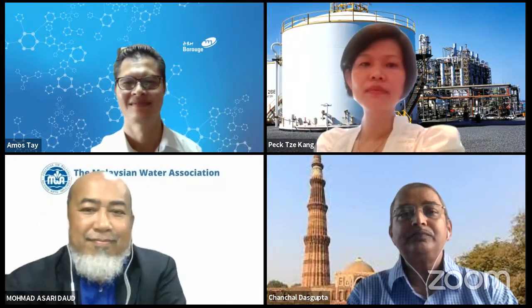Actually, TEPPFA has already stated that a lot of residual PE pipes, 30 years old, 20 years old, dug out from Germany and the UK, that they've done research on, the lifetime is actually predicted to be almost 100 years. There's a lot of data, and a lot of confidence that it's even more than 50 years. But probably for conservative reasons, people still use 50, because it's hard to wrap your head around something more than 50 years, longer than a typical career.